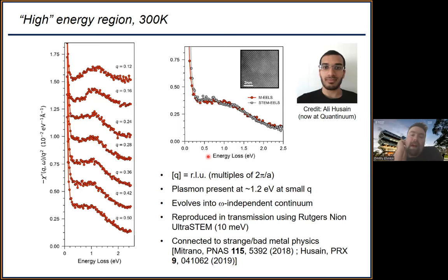Peter, yeah. What is the mechanism of the broadening? Is it just Landau damping? If you calculate the Landau damping, it's too small by about 2 orders of magnitude. So there is a bunch of higher order decay processes that are damping this plasmon. And this turns out to be something we've seen now in a lot of materials.